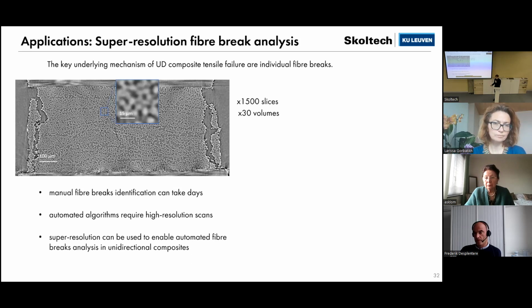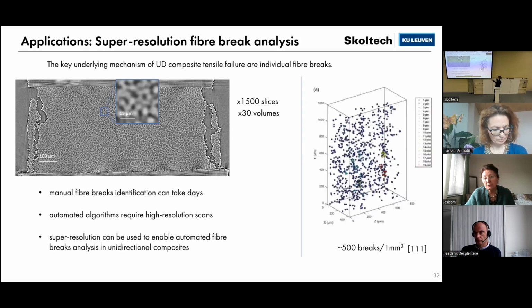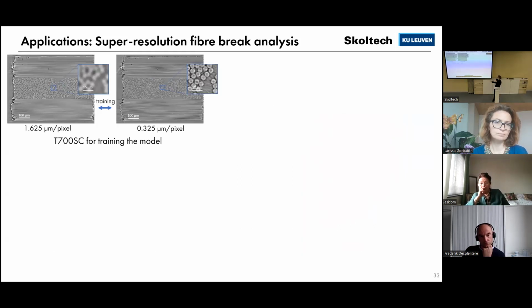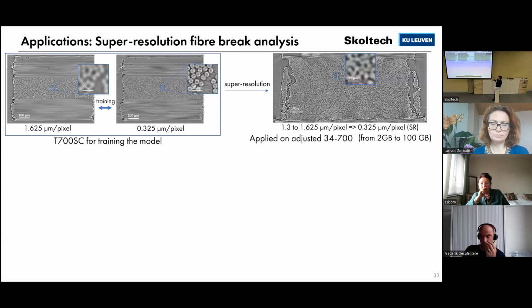So colleagues from KU Leuven will analyze these CT images manually and identify all the fiber breaks. You can see how many breaks there can be in these kinds of images. What was done here is that the model from the super resolution part, already trained on unidirectional carbon fiber composites, was taken and applied to this material. This is a different CT scan, but it was adjusted to look the same as the original one from the training data sets.